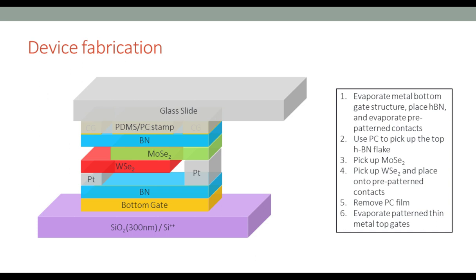And then we pick up a boron nitride layer. We pick it up by placing the glass slide onto the substrate where the BN is, then heat it up and lift it up. And then we can pick up the other layers. Between the 2D materials, there's a strong van der Waals interaction, so we can use the BN to pick up the MoSe2, then the WSe2, and then we place it onto our substrate that we made.